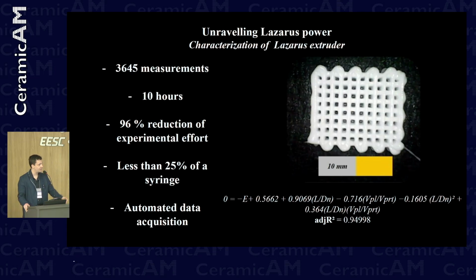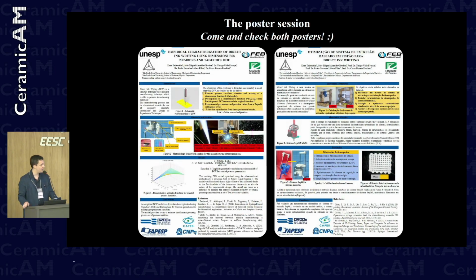And given this characterization effort, we have a model that describes the geometry of the 3D printed filament using direct ink writing as a function of several important process parameters. As you can see, this equation is an implicit equation, so you can also make the reverse work and say, look, I need a filament which has a given width, so what are the best process parameters to generate this width? So I invite you all to come and check both posters.